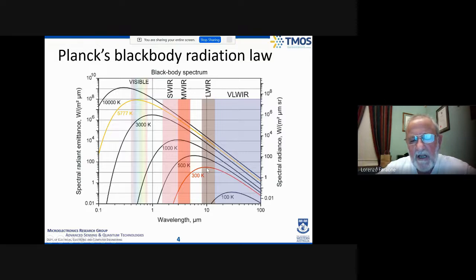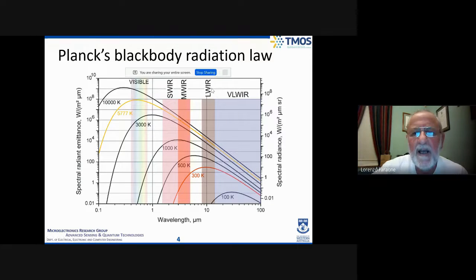Around 10 microns is the peak radiation for something at room temperature or human body temperature. At 500 Kelvin, the peak is closer to the 3 to 5 micron band. As the temperature increases, the peak emission moves to shorter and shorter wavelengths, whereas in the shortwave infrared, there's not much thermal emission.